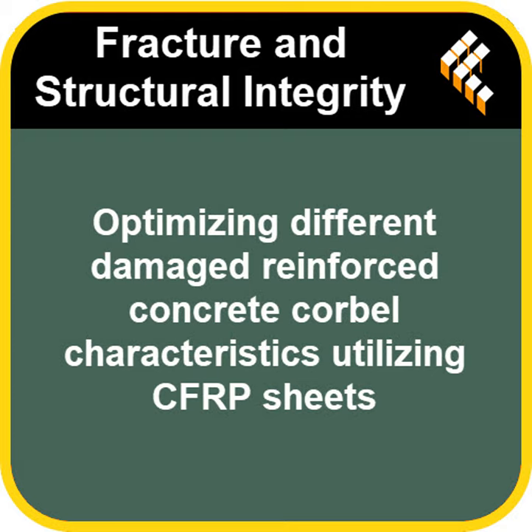Okay, now here's something that really caught my eye. The failure mode. You said all the reinforced corbels failed because the concrete cover came off, not because the CFRP itself broke. That's correct. It wasn't CFRP rupture, it was debonding or delamination initiated by the failure of the concrete underneath the CFRP. What does that tell us? Two main things. One, it highlights just how critical that bond is. Surface preparation, the right adhesive, proper application, it's absolutely paramount for transferring the stress effectively from the concrete to the CFRP. The system is only as good as its weakest link, which in this case was the concrete cover or the bond interface.